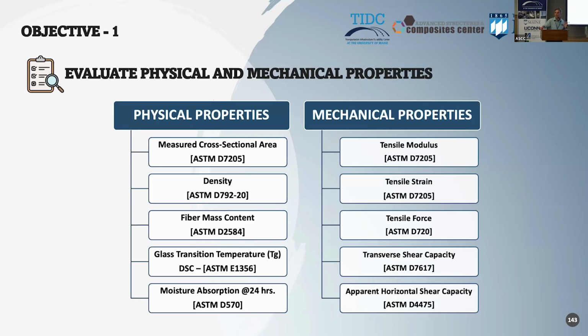One property we're going to put some emphasis on is the glass transition temperature. This is an important property of polymers where the material changes the behavior from what I would call a solid glassy behavior to more of a softened behavior. The material starts losing stiffness. And finally, moisture absorption, which is a key property when we assess durability of these materials. Mechanical properties, we look at 2 tensile properties, modulus and strain. We also look at the capacity in tension of the bar, the tensile force, and then we look at 2 shear properties that have been identified as significant. One is transverse shear, we're trying to cut the bar. The second is horizontal shear, we're trying to split the bar.